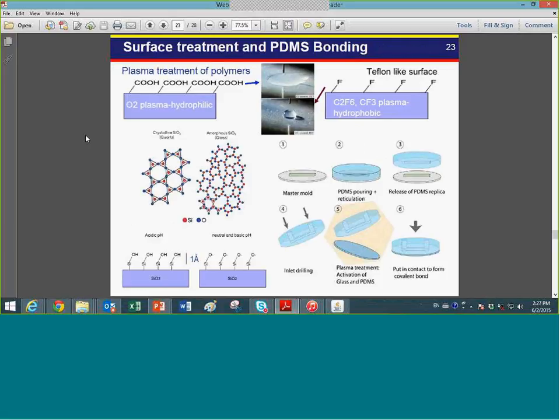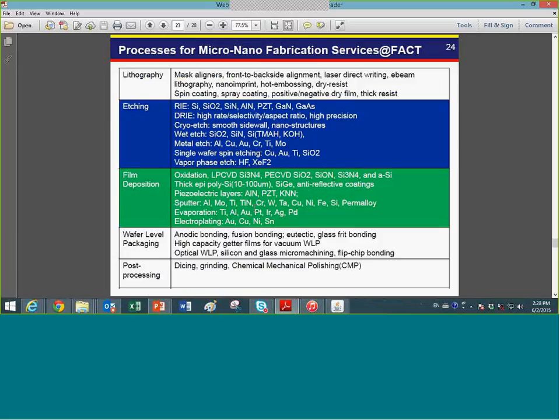Okay, and to modify the surface property of materials, here is just an example: surface treatment and PDMS bonding. This is for microfluidics, which is very popular right now. You can use plasma treatment of the PDMS to make the surface of the material become hydrophobic. This one, like Teflon, makes water on top of it become a ball, and the hydrophilic one becomes very flat. So here are the typical process steps: mold the PDMS and then bond it to glass for microfluidics.